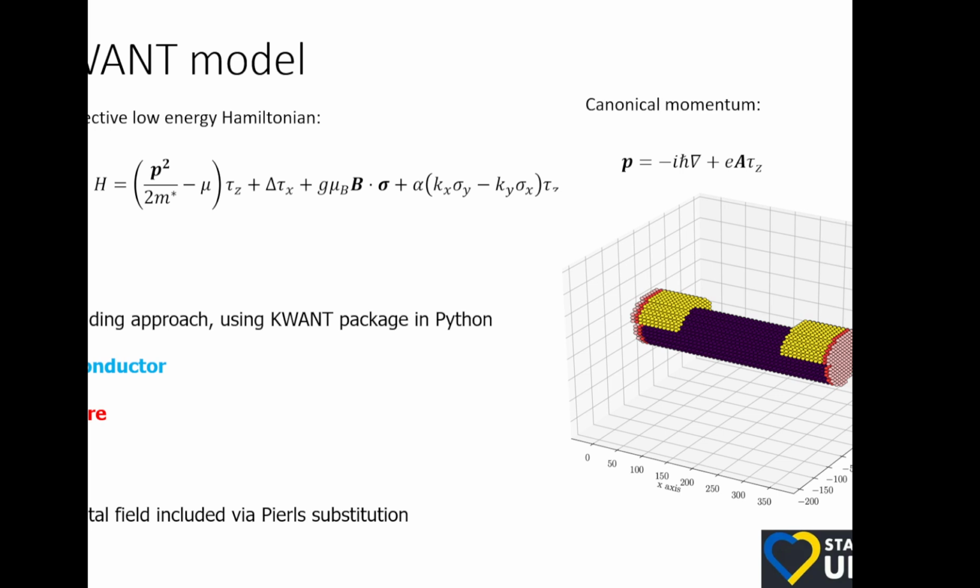The spacing between the superconductors was 70 nanometers in that device, but they deduced from that data that the mean free path was 10 microns, so 100 times more than the available region that they looked at. Right? And so this kind of extreme case, yeah, I think that paper should be retracted, but it's not yet retracted. But that's kind of the extreme case of trusting the theory to compare to your data.